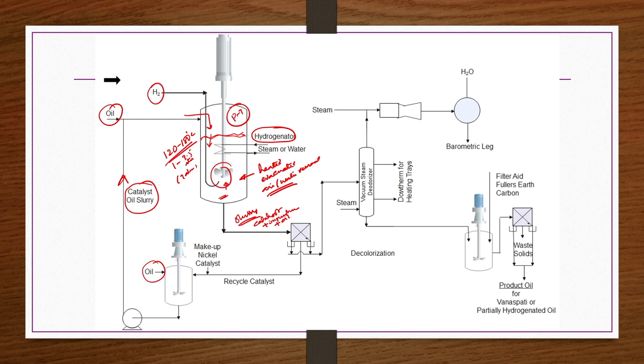However, it is not preferred to go for higher temperatures; more than 200 degrees centigrade is not preferred. Why? Because at high temperature pyrolysis of oils may take place, plus catalyst poisoning or sintering of the catalyst may also take place. If not poisoning, sintering of the catalyst would definitely take place at higher temperature. This reaction usually takes place for 1 to 3 hours depending on the degree of saturation required, the type of oil, and the type of catalyst being used. Because you need long residence time, that is also one of the reasons most hydrogenation processes are batch processes.